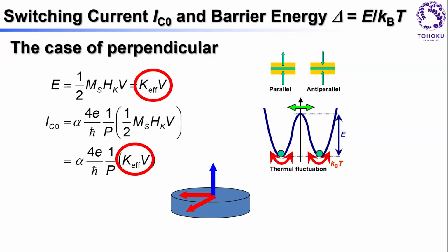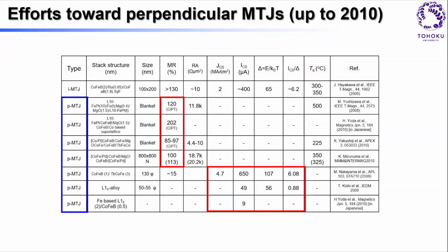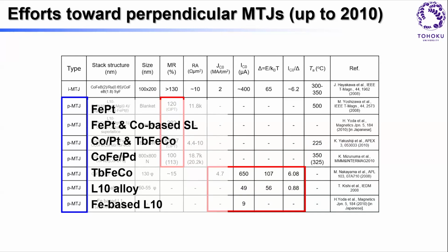So that's the reason why we need a perpendicular easy axis, which gives you the same energy in both expressions. By the way, although this expression is extremely simple, it gives you the right ballpark. If you input numbers with kV over kT of 80 and polarization of 1, it will give you somewhere around 20 microamps, and that's exactly what you see in experiment. Okay. People worked very hard on trying to make perpendicular magnetic tunnel junctions because that's the way to go. But additional structures using iron platinum and so on and so forth didn't work at all because they may give you a perpendicular easy axis, but the resistance change is very small, or you don't see switching at all.